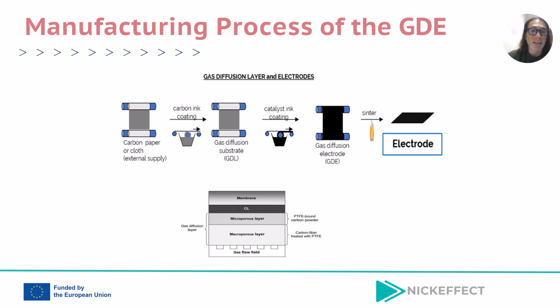Then we apply a catalytic layer to one side of the web. This layer usually contains precious metal particles like platinum mixed with a binder. This layer enables the electrochemical reactions that power the fuel cell. After the layers are applied, the electrode goes through a sintering process. This step helps bond the materials together, improving durability and performance.